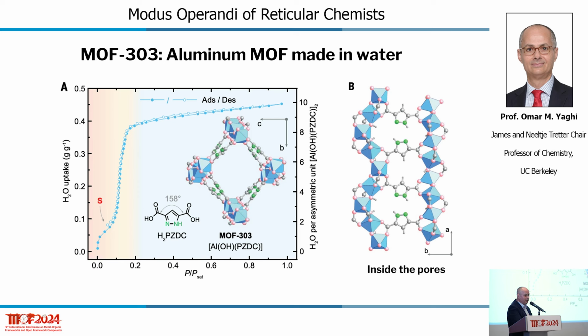The key here, and I'll show you what water is doing in the pores. The key is that the very first water molecules go into the hydrophilic adsorptive site. That water molecule becomes a seed onto which other water molecules bind. And so you have an isotherm that looks like a cooperative phenomenon. Okay, you have a cooperative uptake of water. And when we do water harvesting, we are not taking the first water molecule out. We're keeping it in the pore because it costs you more energy to take it out.